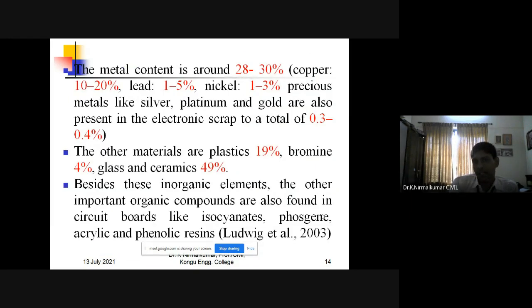Apart from this, metal content is around 28 to 30%. Copper is 10 to 20%. Lead is 1 to 5%. Nickel is 1 to 3%. And sometimes silver, platinum, and gold are present in the scrap at 0.3 to 0.4%. The other materials are plastics 19%, bromine 4%, glass and ceramics 49%.